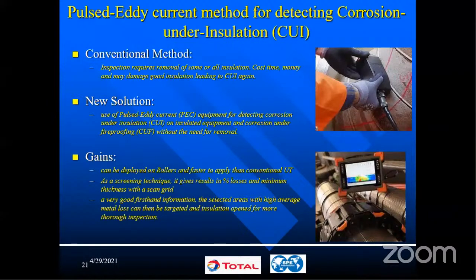So pulsed eddy current is evolving, but it lends itself to high applicability in this type of environment. Pulsed eddy current is an NDT technique where you have these special coils that send a magnetic flux, or magnetic signal, through the insulation, and on the surface of the metal, it creates some eddy currents. The eddy current in itself creates, again, a magnetic field that is read by the signal, and due to the changes of this eddy current, you're able to map the condition of the surface. So this is becoming very applicable for corrosion under insulation survey or even under fireproofing.